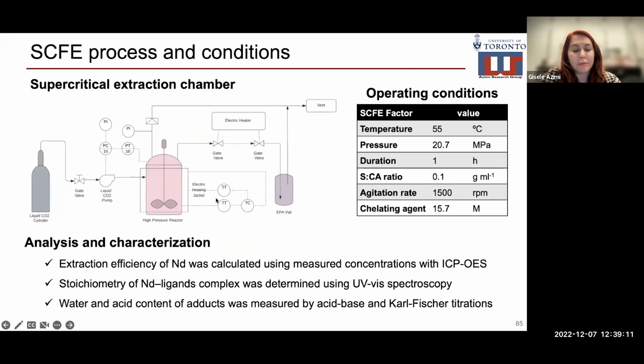This is the schematic of the process that I also showed before. This is the reactor. In this process, we only use supercritical CO2, so we pumped liquid CO2 with no co-solvent. And after the process was complete, we collected the sample in collection vessels and CO2 was released. Here we had 6 operating parameters: temperature, pressure, duration, solid to chelating agent ratio, agitation rate, and chelating agent. Again, to calculate the extraction efficiency, we measured the concentration of the sample before and after extraction with ICP-OES.